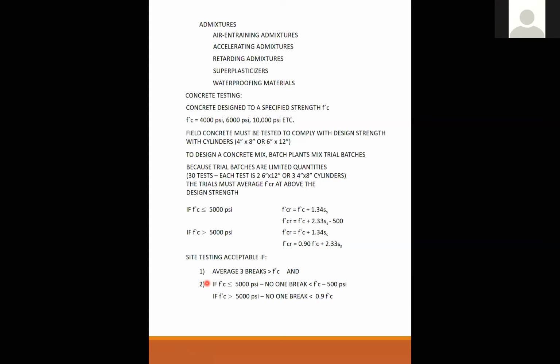Before? So what happens is QC, the deputy inspection at the job site, will write up a non-conformance. That's what it's called. They write up a little ticket and say, hey, we're looking for 4,000, and you had 2 breaks that were under 4,000. We got a problem here. And then what they usually will do is say, okay, let's wait till 56 days and see if it comes up. And if it doesn't come up, now this is pretty darn rare, thankfully, because of all this work that we did up here. But things happen. It does happen. Accidents happen. Somebody double dosed the water, double dosed the superplasticizer, or it sat in the truck in traffic too long.